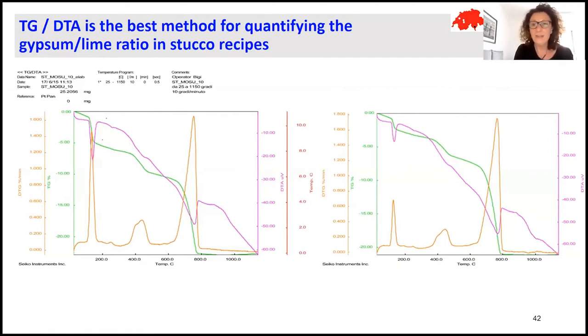We should say and underline the fact that these analyses should always be made together with the microscope analysis, because in this case it's not possible to distinguish the carbonate and gypsum components that belong to the binder from the ones that belong to the aggregate. Because I just make a powder, so I cannot distinguish anymore. I can get the other quantification, for example the presence of an aggregate of calcium carbonate, by making an analysis with a microscope.